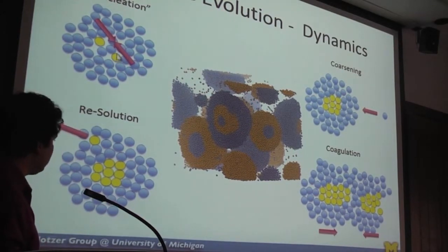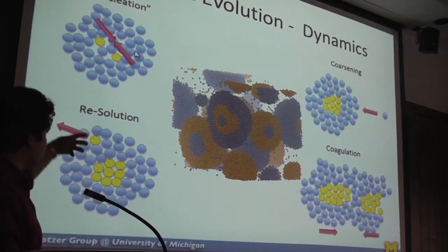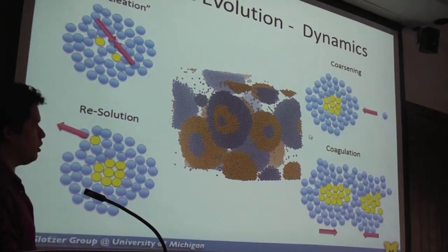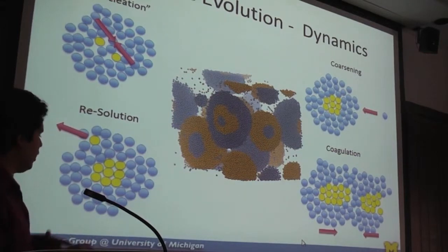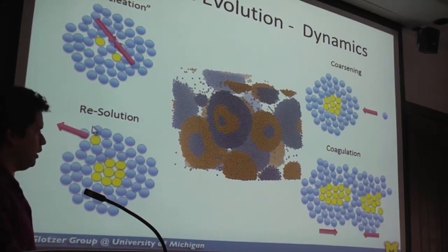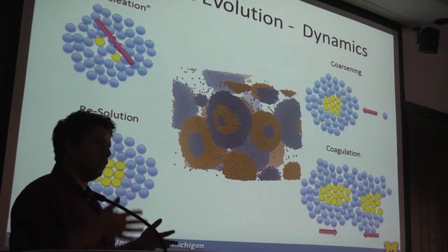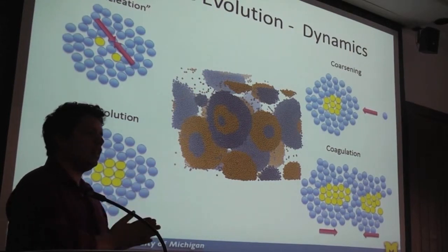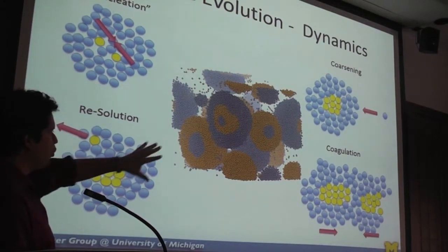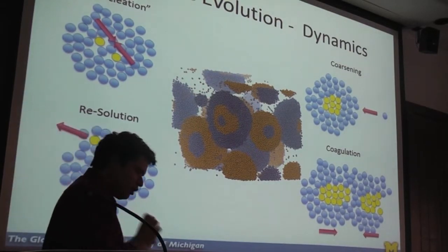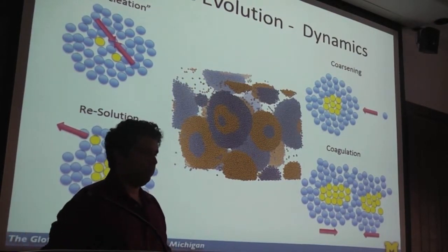Once this layer is nucleated, other particles that switch will be likely to join that nucleus and start building that new layer. Particles are joining the outside, coarsening the size of the aggregate, and some of the particles are also leaving the aggregate. And then particles or aggregates with the surface of similar types come into contact, they share material, and there's a transfer of material between different aggregates. Between these four processes, they stabilize an actual size of an aggregate and the size of the layer.